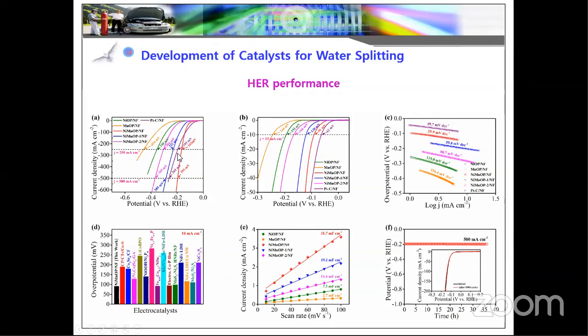The HER performance is also performed. The earlier figures are low resolution and these are high resolution. You can see the onset, and we compared with platinum, the commercially available material. Platinum has 62 millivolts overpotential, and our material is almost close to platinum. So these studies tell we can replace platinum based catalysts. The electron transport kinetics is further confirmed by the HER performances. The Tafel value is very low and close to platinum. Our catalyst has high electron transport kinetics, lower onset overpotentials, and a higher surface area than the other comparative catalysts.